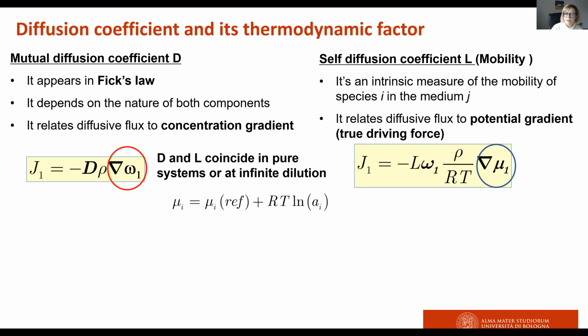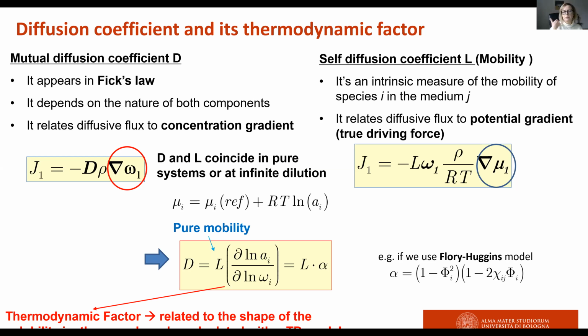So if we rewrite an equation similar to Fick's equation, but using the chemical potential gradient instead of the concentration gradient, we have a different physicochemical parameter that goes under the name of mobility. This is the one relating the flux to the potential gradient. After a few manipulations of these two equations, we can then see that the mutual diffusion coefficient can be seen as the ratio between a pure mobility, which is the self-diffusion coefficient, and the thermodynamic factor, which is actually dependent on the shape of the solubility isotherm, and that can be calculated with one of the models that we just saw for the prediction of the solubility. For instance, if we use the Flory-Huggins model, the thermodynamic factor alpha can be readily evaluated. Note, please, that the self and the mutual diffusion coefficients coincide if we are in pure fluids, of course, or if we are at infinite dilution.